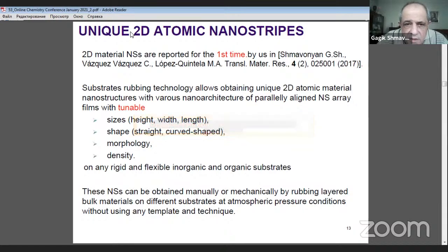And these two-dimensional nanostripes are reported for the first time by us in the following literature. And so this substrate rubbing technology allows obtaining two-dimensional atomic material nanostructures with various nanoarchitecture of parallel aligned nanostripe films with tunable sizes, shape, morphology, density on any rigid and flexible inorganic and organic substrates. These nanostripes can be obtained manually or mechanically by rubbing layered bulk materials on different substrates at atmospheric pressure conditions without using any template and technique.